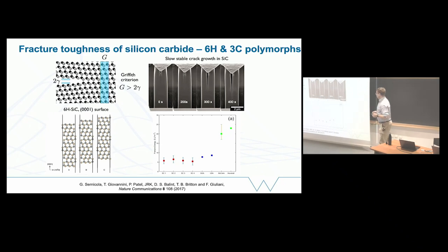So we did this a few years ago in collaboration with an experimental group at Imperial led by Finn Giuliani. They very carefully set up a piece of single crystal silicon carbide. They stuck a wedge in the top up here, an indenter, and they pushed very slowly and very carefully under a microscope. And the crack is growing very stably, so it's taking 400 seconds to move by a few millimeters.